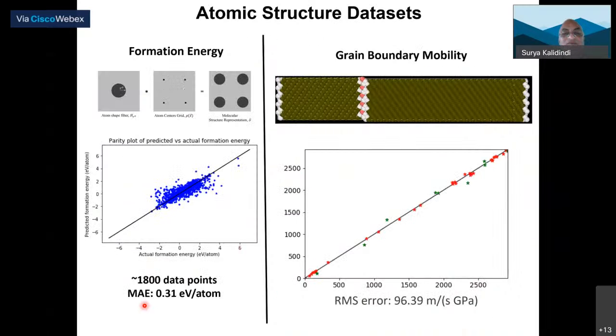It's also not restricted to mesoscale. You can do the same at the atomic scale. Same thing happens: we take atom positions, we voxelize them, then we do two-point correlations, PCA where necessary. It's more or less the same feature engineering, but maybe slightly different in the model building part. Here there's a large data set of compounds, and we are predicting the formation energy. It does a decent job over 1,800 different compounds.